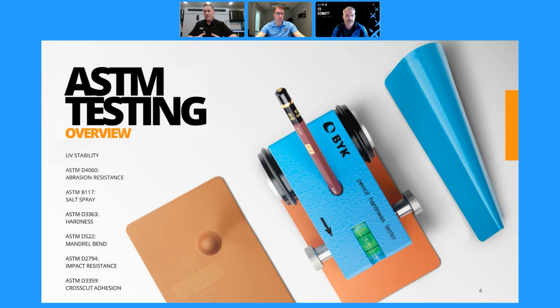Through all of these tests, I saw 0 red flags. I saw 0 decrease in performance. I actually saw on a couple colors, we did get increased performance on a couple of them, but we were able to maintain the same UV stability, the same abrasion resistance, the same corrosion hours, the same hardness. We were able to get the same results on mandrel bend, impact resistance, and then the most important, the cross-cut adhesion. The cross-cut adhesion performed very well on the 10X.